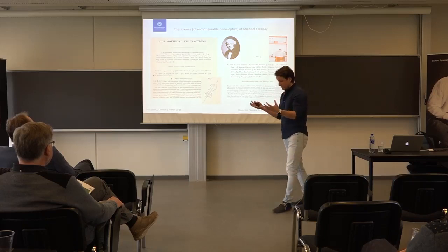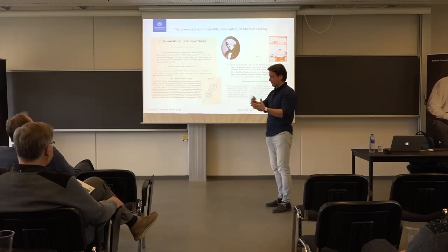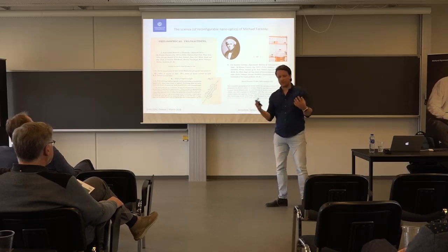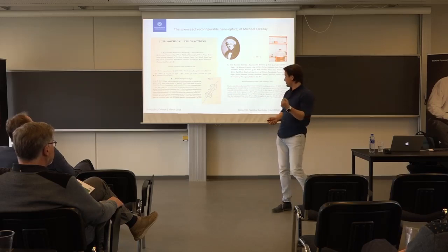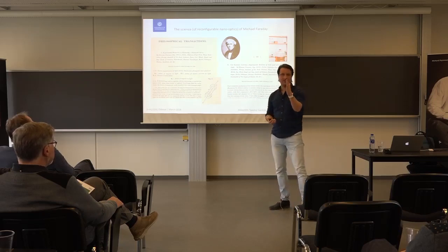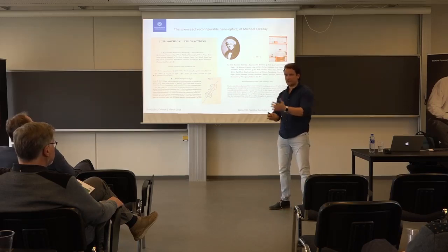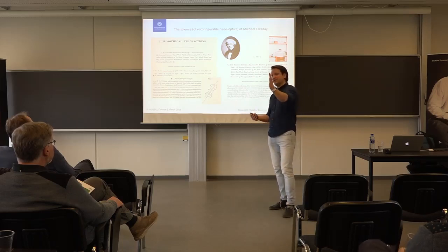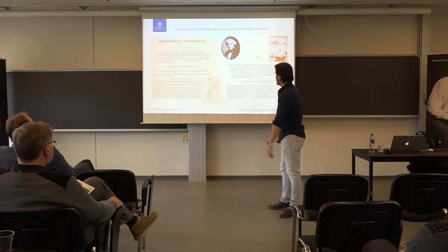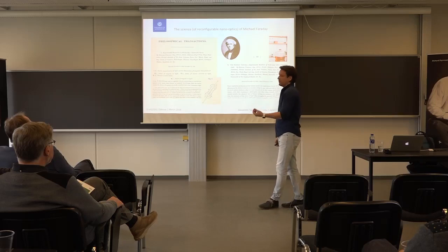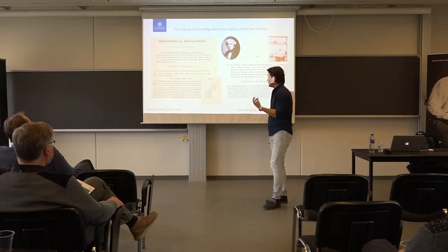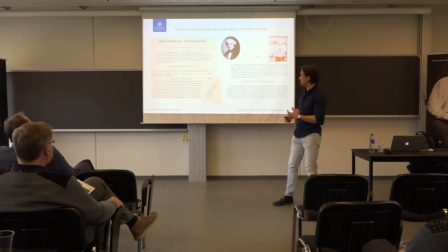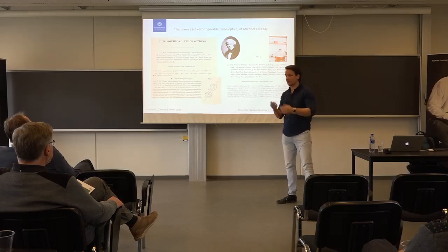You send a light beam through that material and then apply a magnetic field to it, and it turns out that the polarization of the light starts to rotate or become elliptical. When you remove the magnetic field, it becomes linear again, as the original incoming polarization of light. That is the magneto-optical effect, which is called the Faraday effect in transmittance, and the Kerr effect in reflectance.